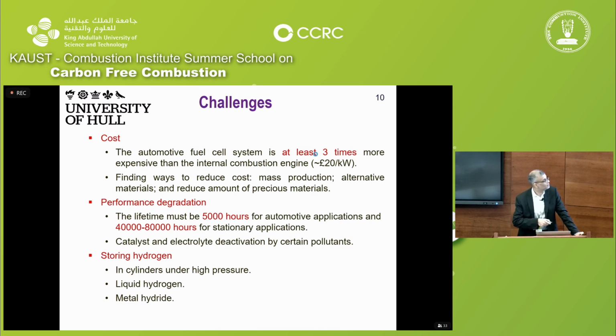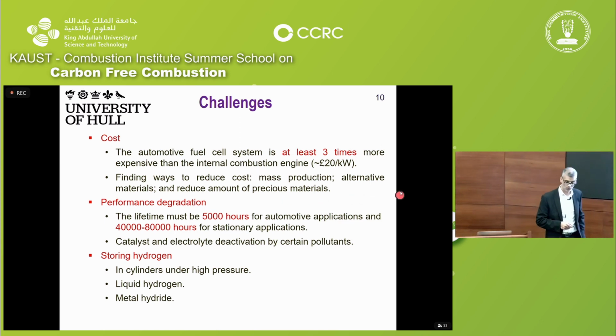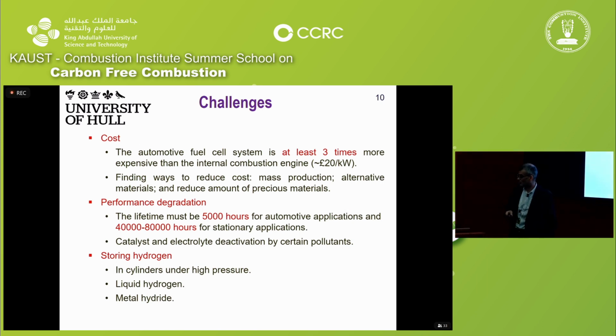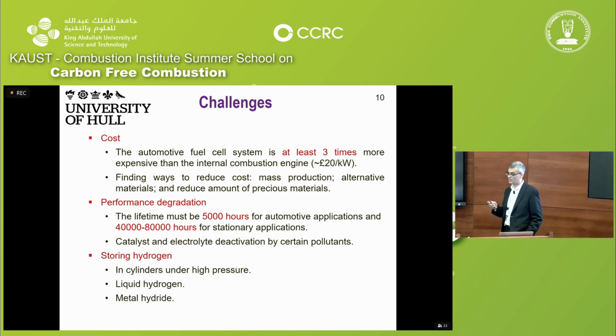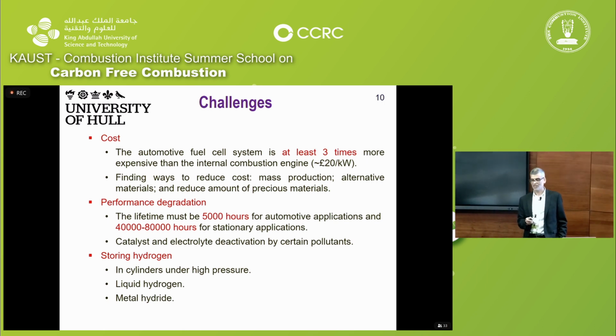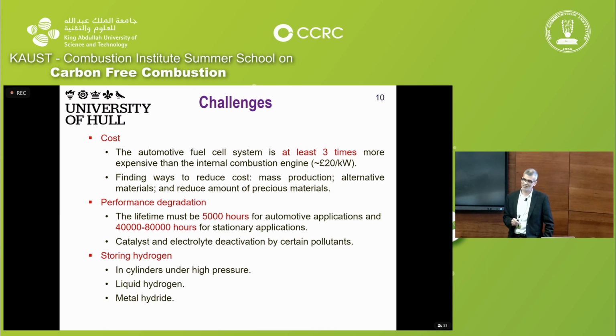The third method to reduce the cost of the automotive fuel cell system is to reduce the amount of catalyst, especially platinum catalyst used in polymer electrolyte fuel cell. As mentioned by Jamie, the amount of platinum used in automotive fuel cell systems, on Toyota Mirai for example, is a bit significant. I think I have made some rough calculations, and it turned out the amount of platinum used in Toyota Mirai's fuel cell stack is around 35 grams, which is a lot. This has to be substantially reduced for the fuel cell to be competitive with the conventional ones.